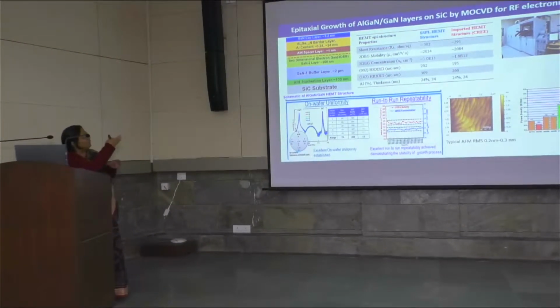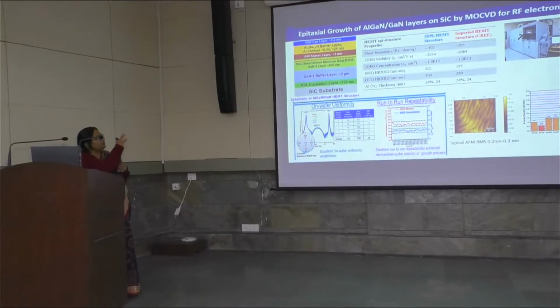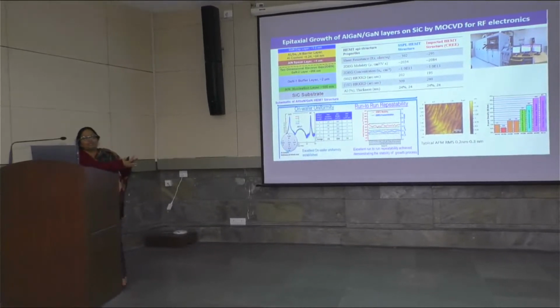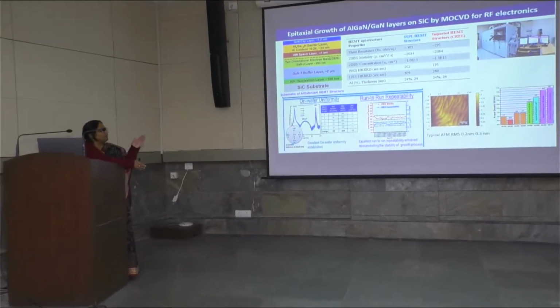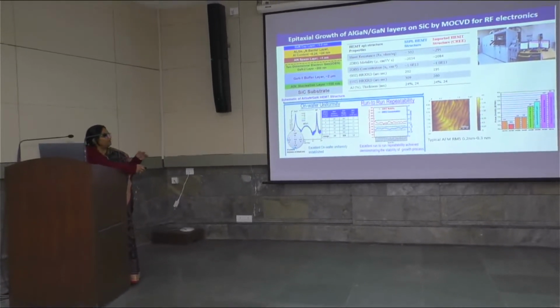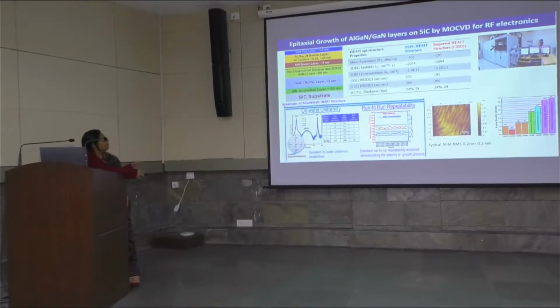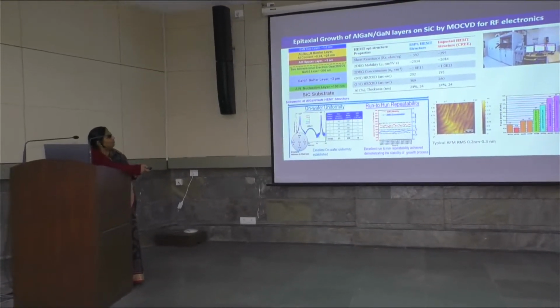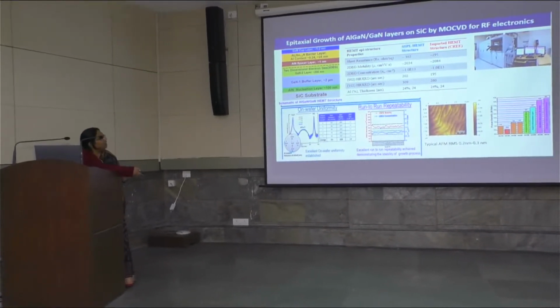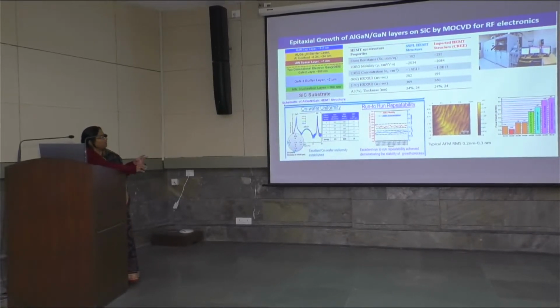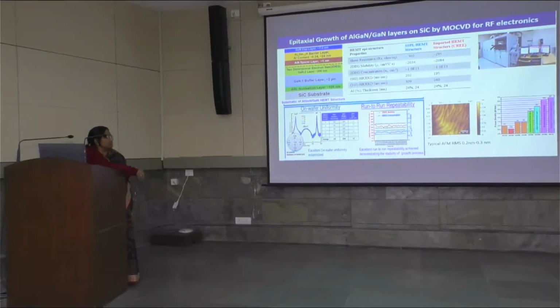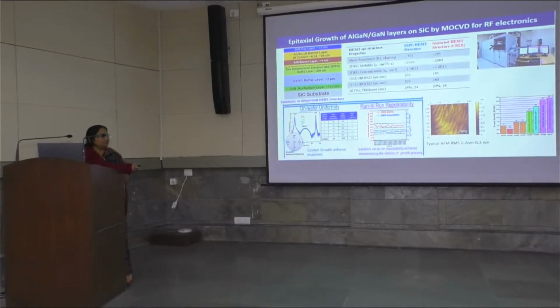And then we have developed the device grade material. It is not as trivial as it sounds because it takes a lot of iterations and characterization before we reach there. And so then we can look at the on-wafer uniformity and run-to-run repeatability. And typically this is the AFM measuring the surface roughness, which is as good as state-of-the-art material available.